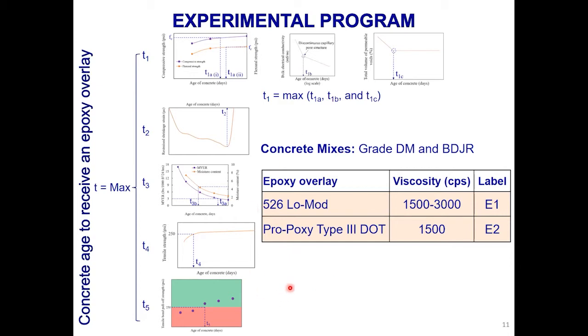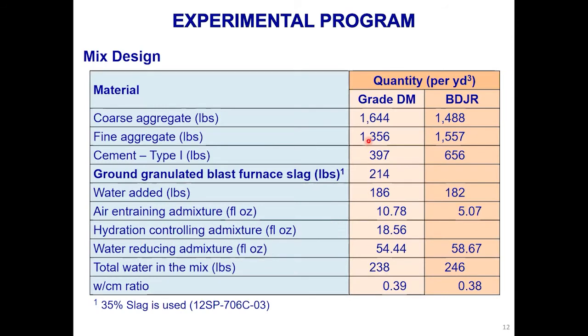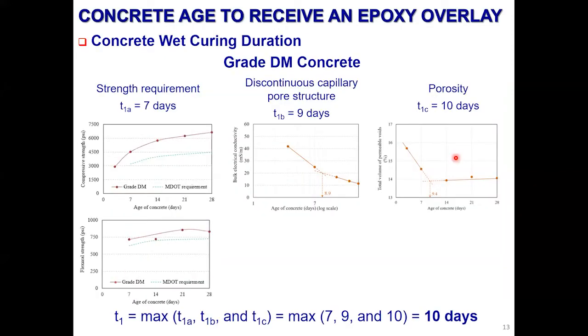So we developed an experimental program to evaluate all these parameters. For that, we use 2 epoxy overlays, and we consider 2 concrete mixes. One with slag as a supplementary cementitious material. The other one only had type 1 cement. When we look at the curing duration for the mix with slag, we need to go up to 10 days. The typical curing duration is 7 days, because by 7 days we will have all the strength values satisfied.